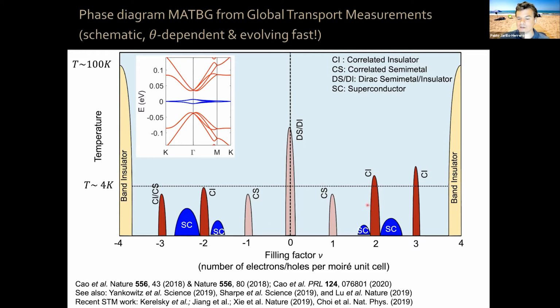But then as you fill each integer number of electrons per Moire unit cell, something interesting happens, okay? At 2 and -2 and at 3 and sometimes at -3, what you see are correlated insulator or correlated semi-metal states. At 1 and -1, you have correlated semi-metal states. At 0, at charge neutrality, you have a Dirac semi-metal or a Dirac insulator state, depending on details, okay? And then as you dope away from 2 holes per Moire unit cell or 2 electrons per Moire unit cell, you have superconducting domes. This is usually the most prominent when you dope with extra holes the correlated insulator state at 2 holes per Moire unit cell.